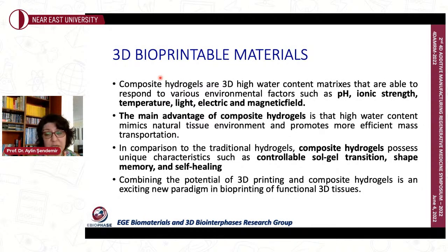So you can print at some condition, but then increase the stiffness, increase the hardness, and therefore the shape fidelity by some external effect. And usually not only hydrogels, but composites of hydrogels, because most of the hydrogels that we use today do not have shape memory effects, the properties. They are not most of the time stimuli responsive, but we use different additives to make composites of these hydrogels to achieve that environmentally responsive effect.